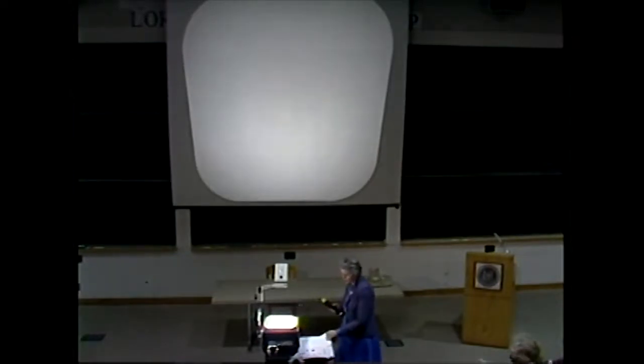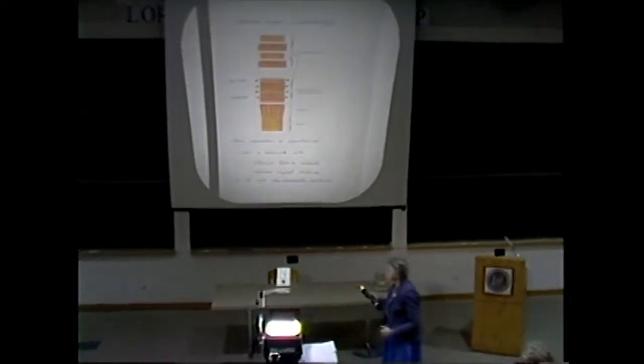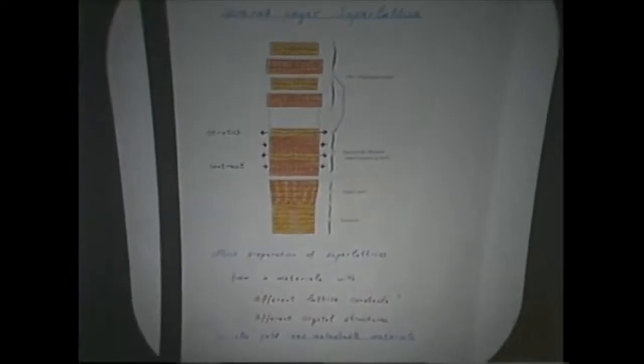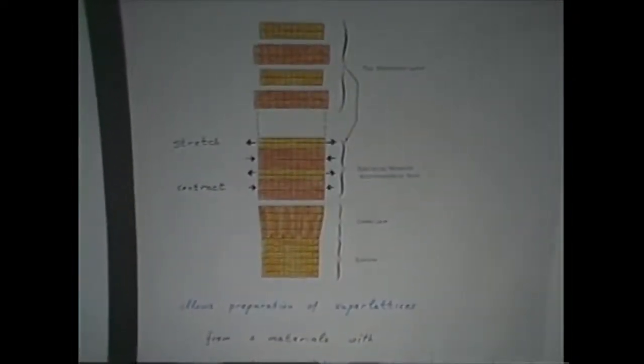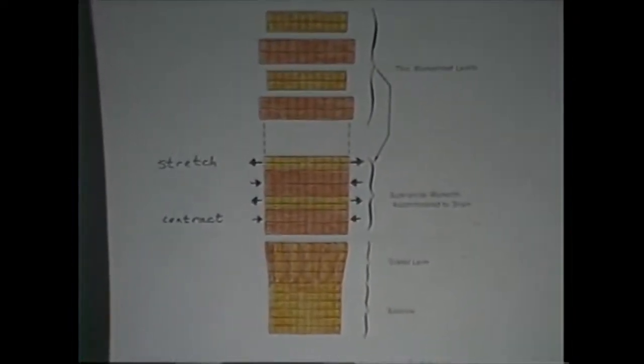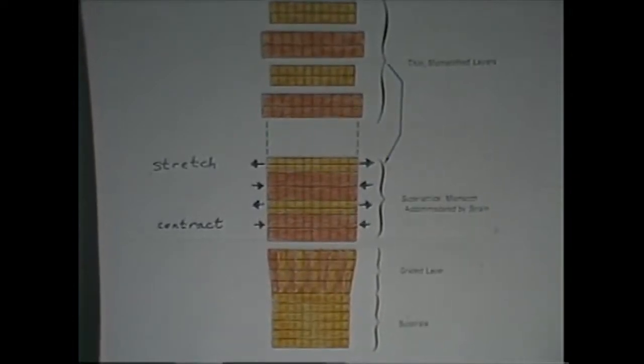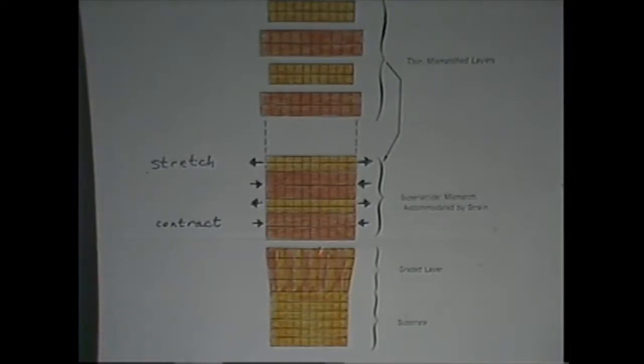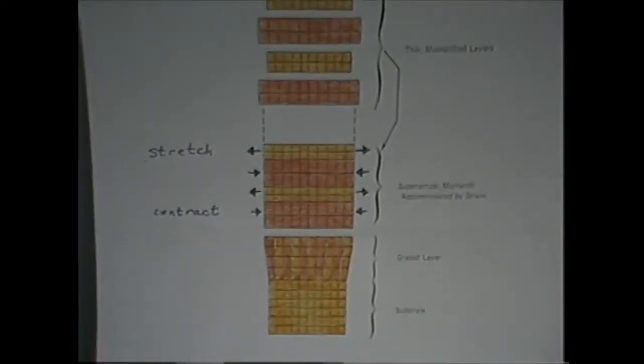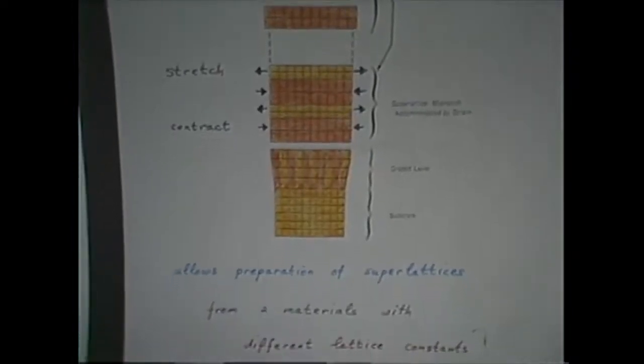Now, what we see here also occurs in molecular beam epitaxy. When you make a strain layer superlattice, it's exactly the same concept. We have a material with one lattice constant, another material with another lattice constant, and when you put very thin layers together, the material with the small lattice constant will stretch, and the material with the large lattice constant will contract, so that they form together a system with some kind of compromised lattice constant, which you can control with the graded layer that you put as the substrate.